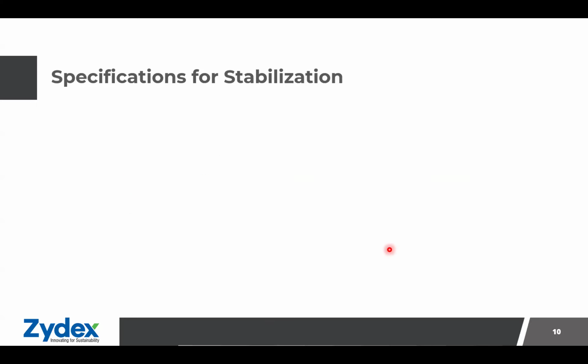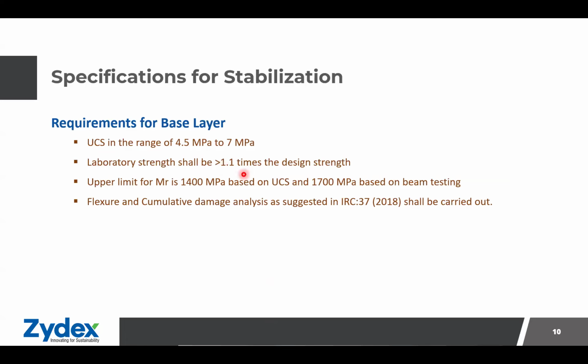Now, for the specifications for the stabilization, first for the base layer, we need to achieve the UCS in the range of 4.5 MPa to 7 MPa. The laboratory strength shall be 1.1 times higher than the design strength. Also, there is an upper cap on the modulus value that we can consider. For the modulus value based on the UCS empirical relation, we have an upper cap of 1400 MPa, whereas we have an upper cap of 1700 MPa if we do the beam testing. Also, the guidelines suggest to do the flexure and cumulative damage analysis suggested by IRC 37, 2018.